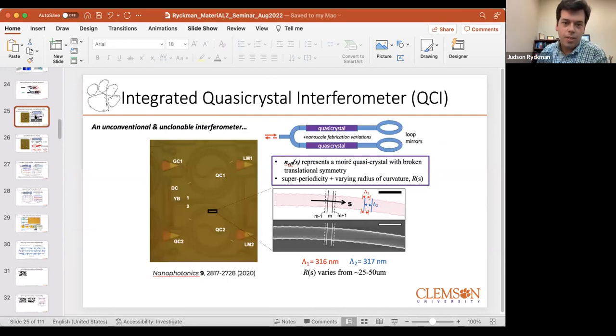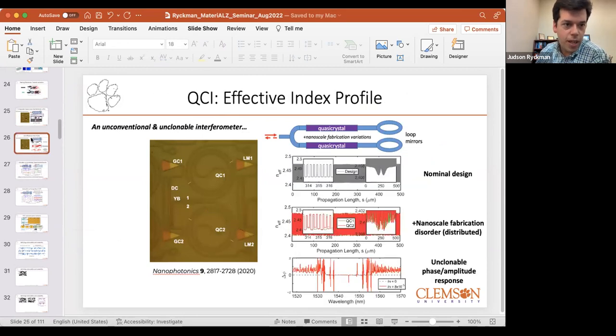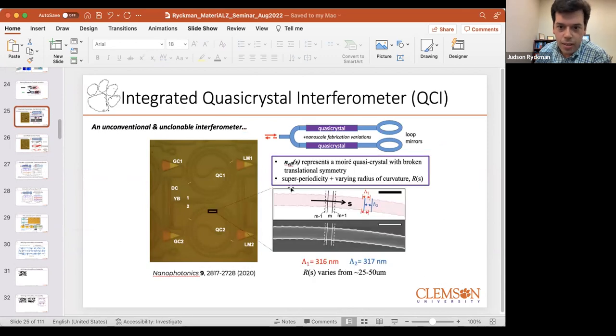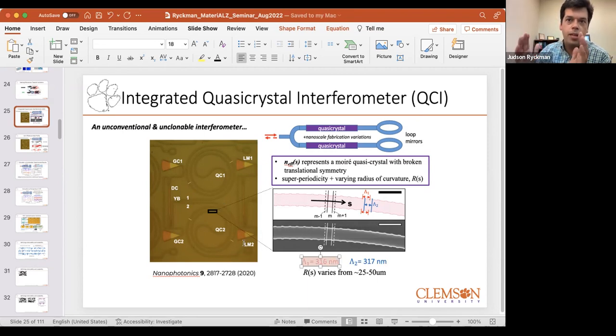Yeah, that's a really good question, and I probably don't explain that that well, but there is indeed a very intentional design. The fact that we choose this period to be 316 and this period to be 317: the 316, if it was just this, would produce a Bragg diffraction peak or a Bragg mirror around 1550, so that would put band edges around 1550. On the band edge there's a very high sensitivity because light slows down, so it becomes more sensitive to perturbation.